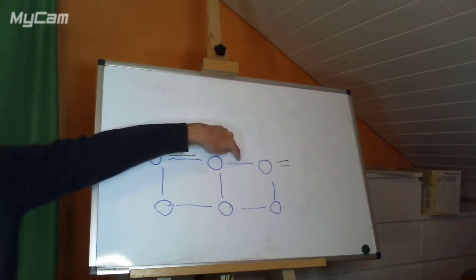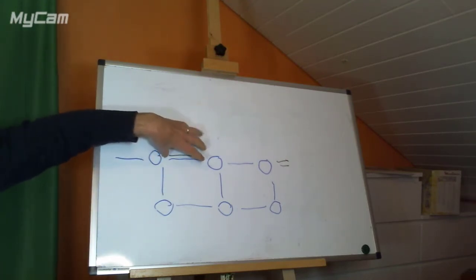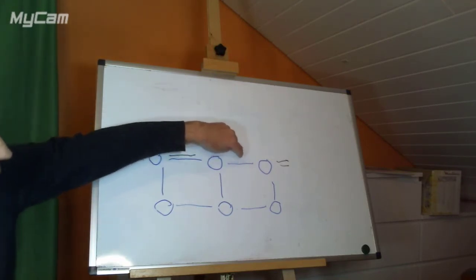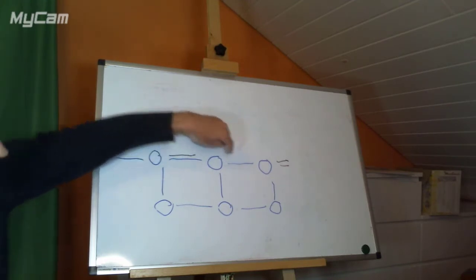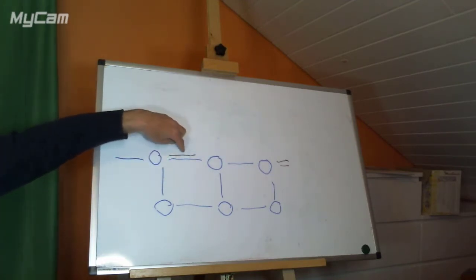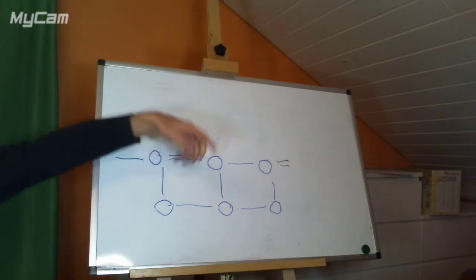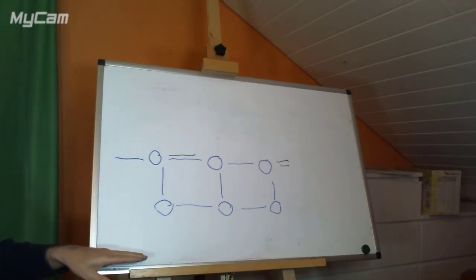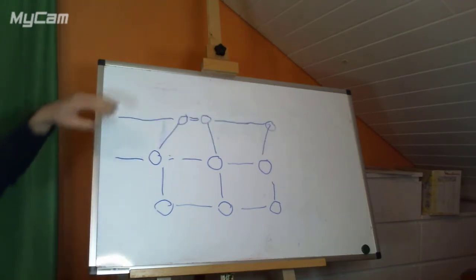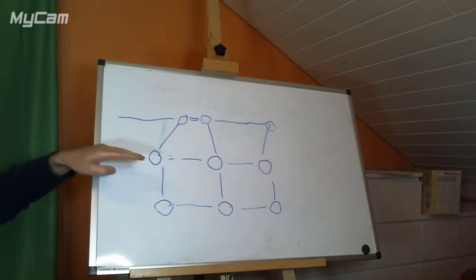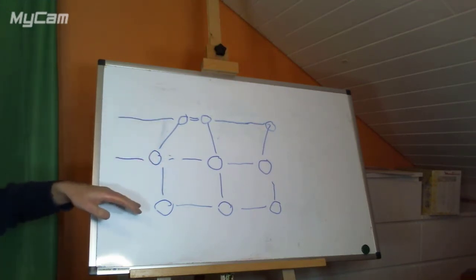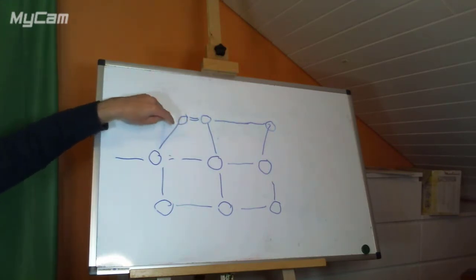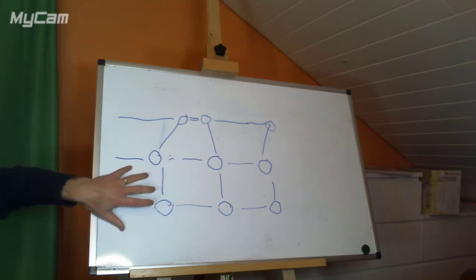That's good, because otherwise our surface would just react with anything. But it's still quite reactive because obviously this is strained. This bond is unnaturally stretched because this double bond is smaller. It's stronger, so it will become smaller, and that will stretch this one. So this one is stretched and strained. This one is stretched and strained because it can't be as short as it would like to be. All of these bond angles are weird. Something is going on, and then it doesn't fit to the rest of our structure. What this means in reality is that the layers below our surface, several layers below our surface, are also distorted because the force on these atoms is incredibly high, and so it will distort the other atoms slightly lower.